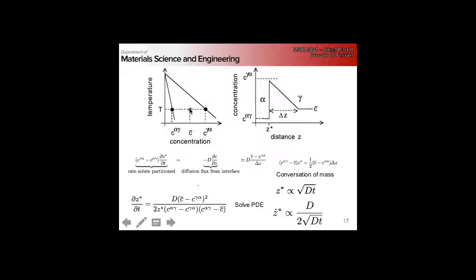We come down, we start to partition by the lever rule. So that means if this is ferrite here, this is the ferrite austenite interface. Here's our overall carbon concentration of our austenite. We now have this diffusion profile out in front.